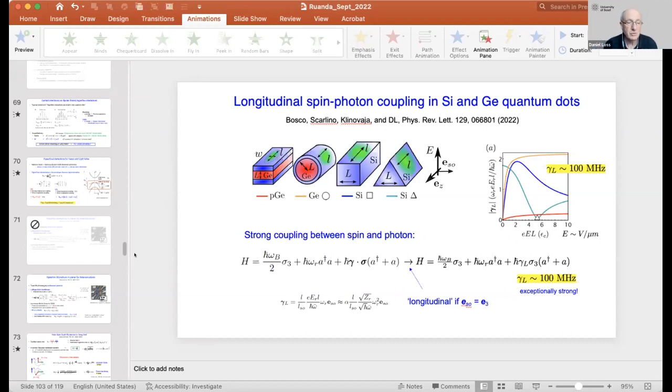It can introduce also charge noise if it's local, and if there are, let's say, dangling bonds, which will affect then the effective splitting of the qubits. Strain can also be induced just by the gates, the metallic gates, which are on the surface of the material, also because there is mismatch of lattice constants of the metal with the semiconductor. And so strain, in the end, is a very important aspect, which helps actually then to kind of optimize the performance of qubits. But it's also very difficult to understand in detail, because not all device structures are known in such great detail that we know exactly in which direction the strain and what non-uniformity the strain has.